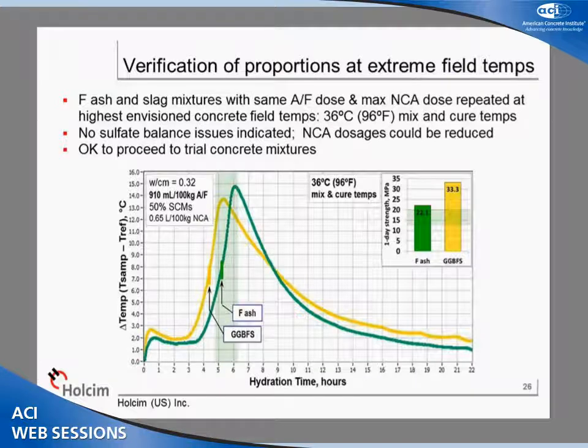The final thing to do in the sequence of events is to check and see if you're still going to be okay at your highest envisioned field temperatures in concrete. So we've bumped our mix and cure temperatures up to, in this case, about 96 degrees Fahrenheit. We've reinvestigated the F-ash and the slag mixes. Of course, they are actually setting faster now. We could even reduce the non-chloride accelerator dosage. The one-day strengths are now ample.